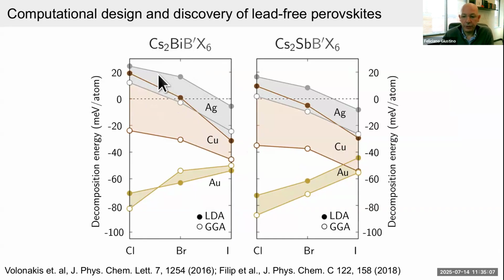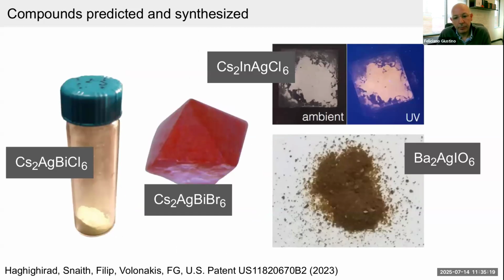So these simple observations based on total energy calculations has led us to the prediction of a few compounds that should be stable and should have interesting optoelectronic properties. And actually, these compounds were synthesized by our collaborators when I was then at the University of Oxford. So this would be the group of Professor Snaith, who is one of the discoverers of perovskite solar cells. And the compounds in question are the silver bismuth halides. So these are silver bismuth chloride, silver bismuth bromide, also an indium silver chloride. And later we also found an oxide perovskite where the silver surprisingly acts as a high charge cation.